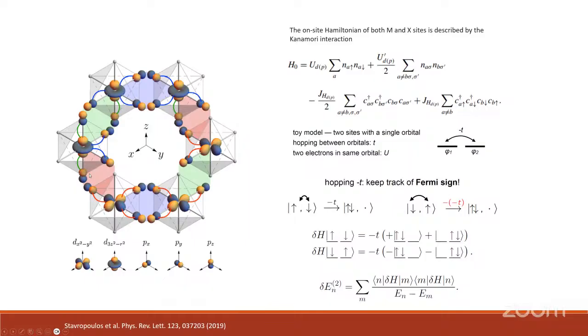So we have to consider very carefully that, even though they are all nearest neighbor transition metal sites, they stay in different environments, so that when we consider the spin interaction, maybe three different nearest neighbor hopping terms should be considered, right? So your eventual spin model would be different along three different directions.